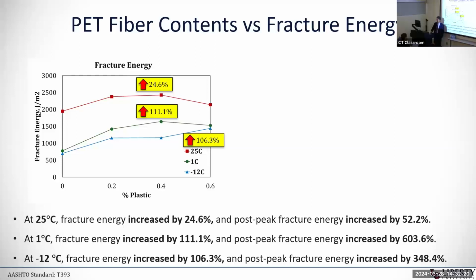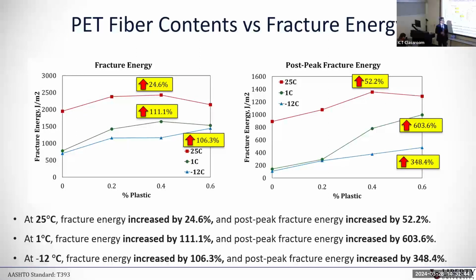Hyunjun Yu in 2014 used a PET plastic, and he found 0.4% is the optimum because he found the same trend of the fracture energy increasing and decreasing. But we tried to look a little bit more, because this is a bulk fracture energy response, including pre-peak and post-peak. So we zoomed in and looked at the post-peak fracture energy, because these fibers are actually bridging the crack.